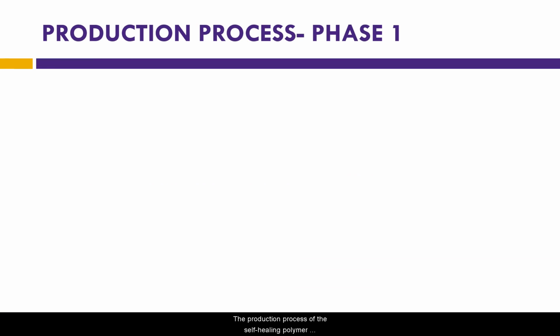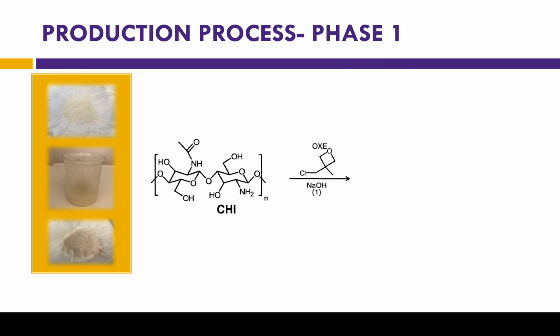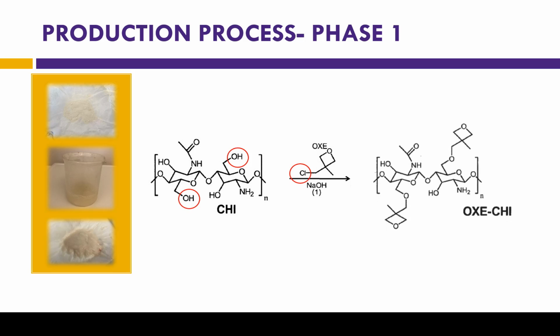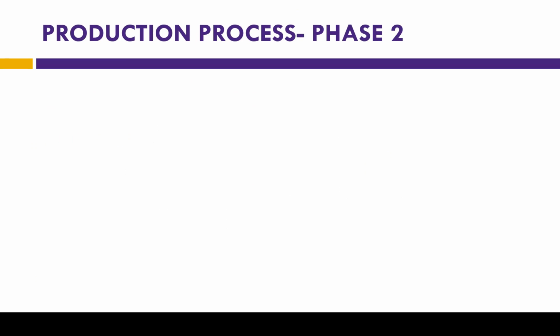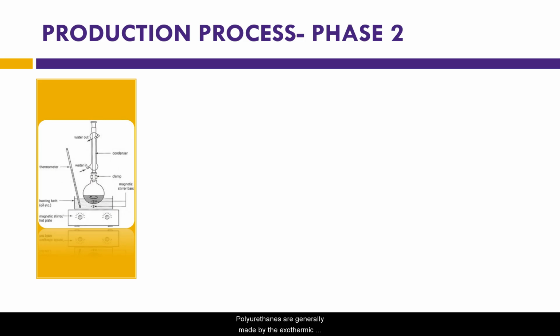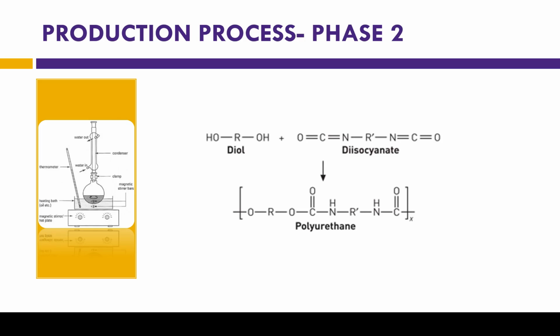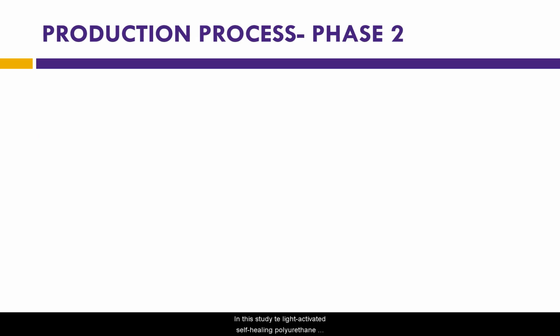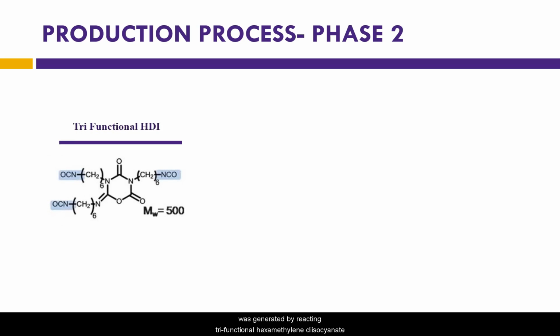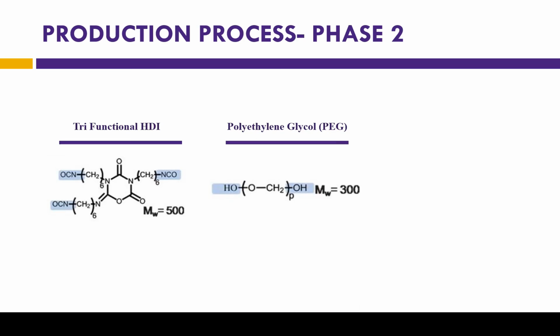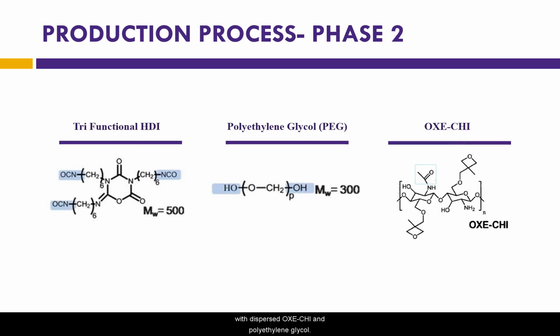The production process of the self-healing polymer consists of two phases. In the first phase, the oxetane-substituted chitosan is produced by reacting the OH group of chitosan with chloromethyl oxetane. In the second phase, we have to produce the self-healing polyurethane. Polyurethanes are generally made by the exothermic reactions between alcohols with two or more reactive hydroxyl groups and isocyanates that have more than one reactive isocyanate group. In this study, the light-activated self-healing polyurethane was generated by reacting trifunctional hexamethylene diisocyanate with polyethylene glycol and dispersed oxetane-substituted chitosan.